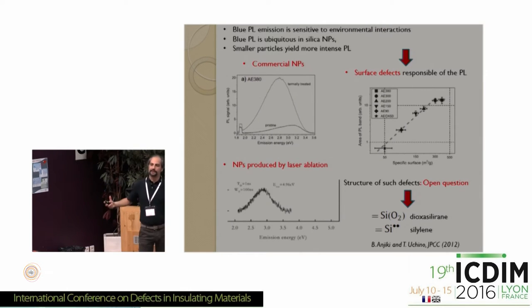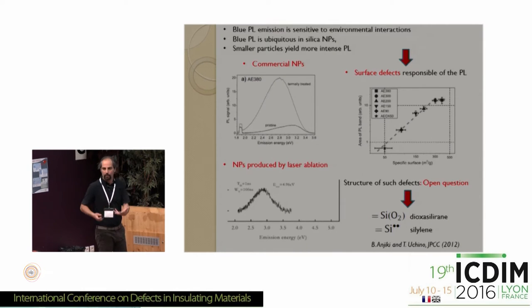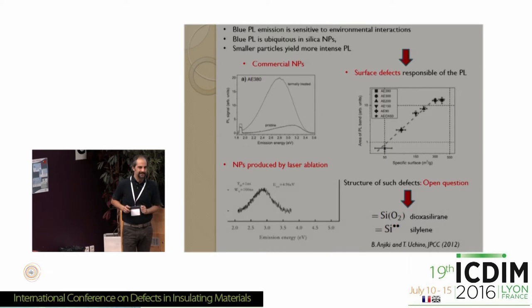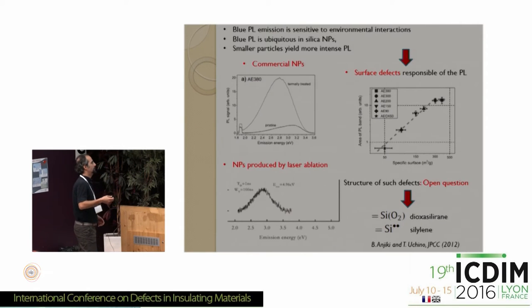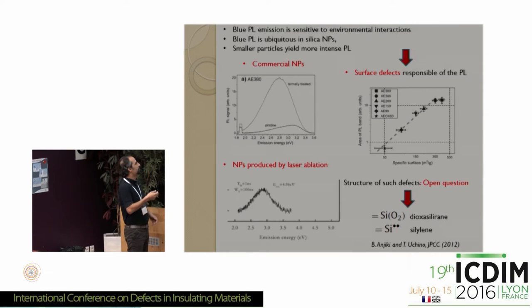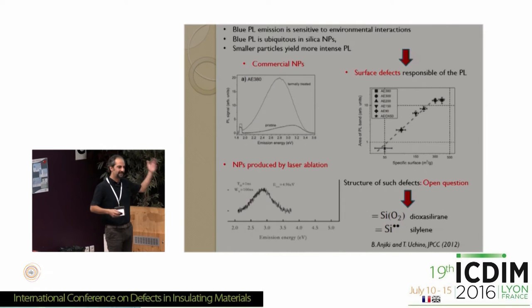Of course, the fact that you confine the system to a nanometric scale means that surface-related electronic states become very important in determining the optical properties. However, it's still an open problem to understand which specific surface moieties are associated to the electronic states that give rise to this emission. The most common interpretation, which is currently referred to in the literature, is due to Uchino's group, and attributes this luminescence to defects present on the surface. But this is actually an open problem.